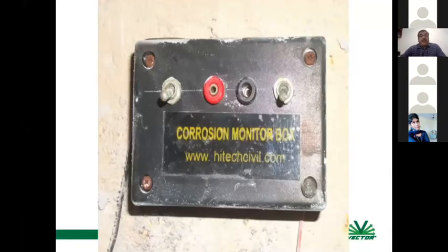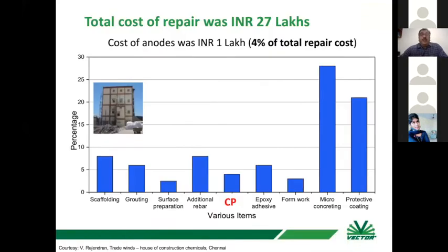And there was a monitoring box, and we regularly monitored the corrosion, the current from the anodes, and it is performing. And again, when we do the cost analysis of the entire cost, the CP percentage cost was very low compared to the other parts. So we found, and even published a paper, that the cost of CP might seem to be high initially as the unit cost, but when it comes to the entire repair system cost, it's a fraction.